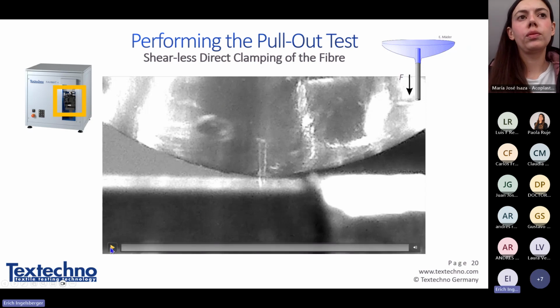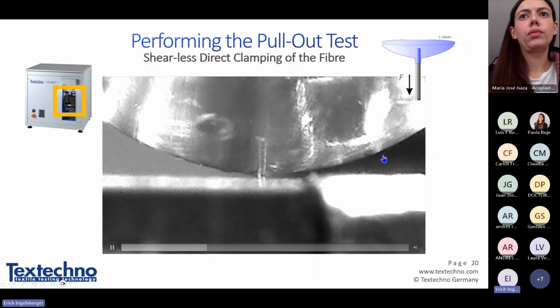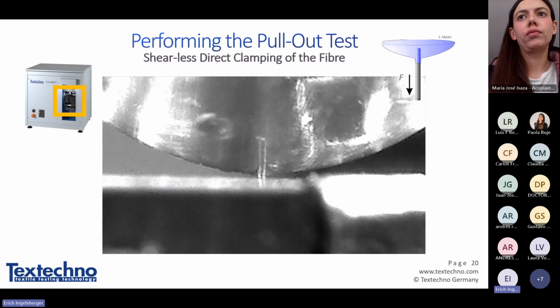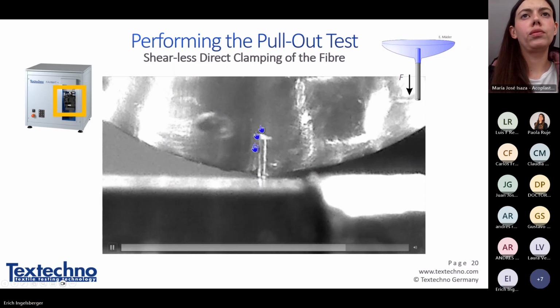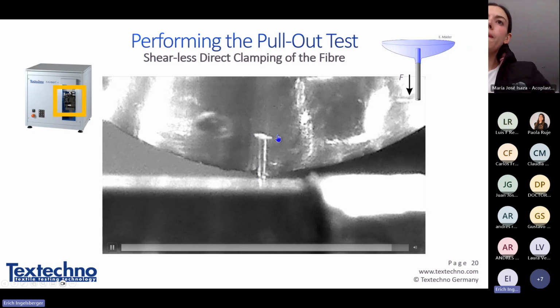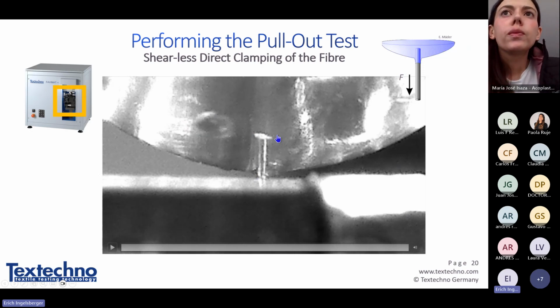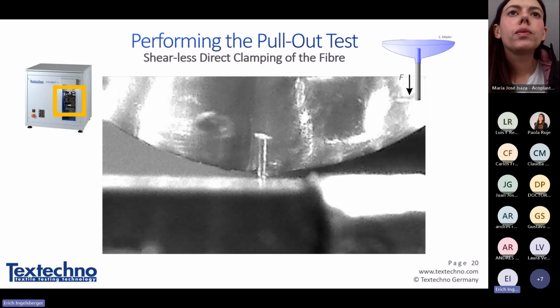When you start pulling out, you can see that the fiber will first create a crack. You will see this in one moment. Now the crack moves up until it is completely debonded, and then the pull out will continue, but only against the slippage of the fiber inside the matrix.